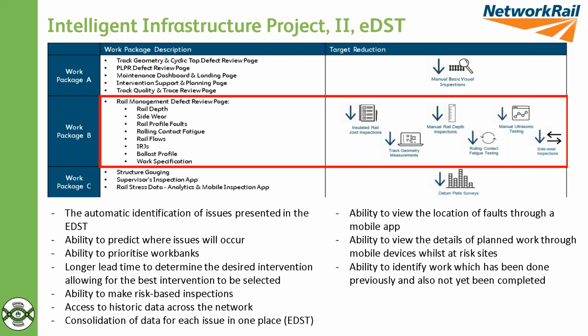So getting the right data there, and that's some of the things they're looking at with rail depth, which is what I've just shown you from the UTU, side wear measurements from the systems on the UTU, looking at rail profile faults. Have we got problems where we've got localized head loss, we've got perhaps excessive side wear, eddy current RCF, rolling contact fatigue, bringing in the normal ultrasonic information, making sure we've got other key features. We know where our insulated rail joints are, things like that. We can better make use of that information if it's synchronized.